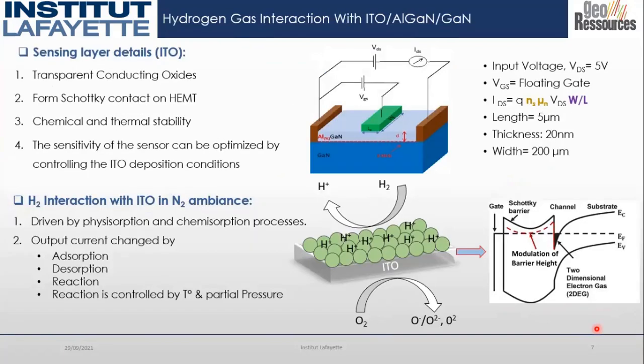So now, why do we choose indium tin oxide as a gate material? Indium tin oxide is a degenerate semiconductor metal. Depending on the growth parameters and temperature, this ITO can act as a metal or a semiconductor. So ITO provides tunable electrical characteristics and is compatible with the HEMT structure by forming a Schottky barrier with the semiconductor interface. And most importantly, this is a chemically and thermally stable metal. We deposit this ITO as a sensing layer for our device, and the input bias is 5 volts and the gate is kept floating.